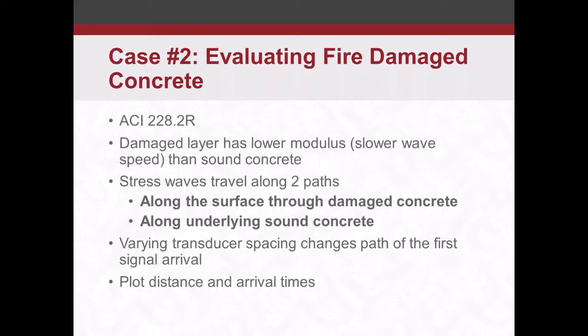So ACI 228.2 talks about a way to use ultrasonic pulse velocity to check the depth of fire damage in concrete. And the idea is the damaged layer has got a lower modulus, which gives it a lower wave speed than the underlying sound concrete. And what happens is these stress waves, these ultrasonic pulse waves, will travel along two paths. The first path is along the surface, and the second path is along the sound underlying concrete.